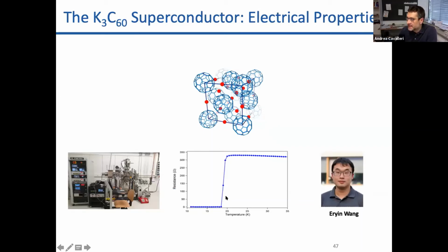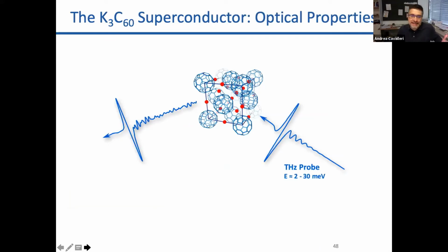This is a measurement on materials that we grow in our lab with molecular beam epitaxy, making thin films of these materials, grown by my postdoc, Eryin Wang. And so this transition, of course, manifests itself in all the expected features of superconductivity, but it can also be detected optically by doing terahertz reflection measurements.